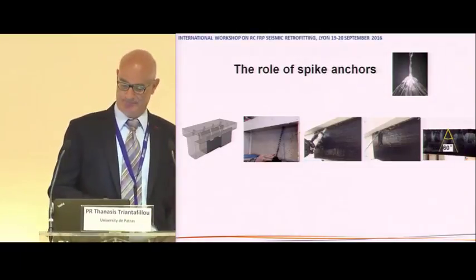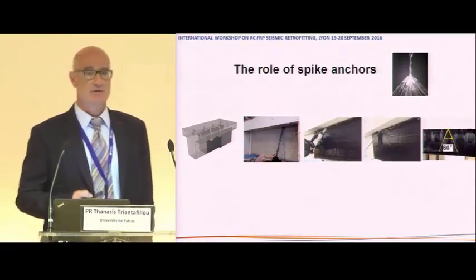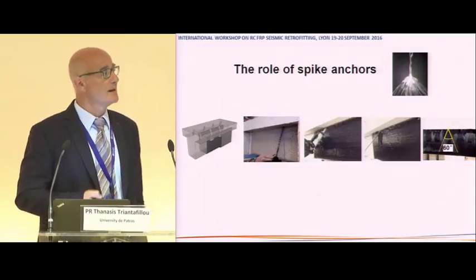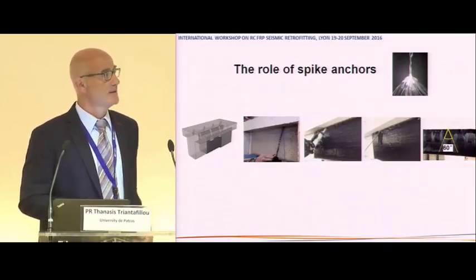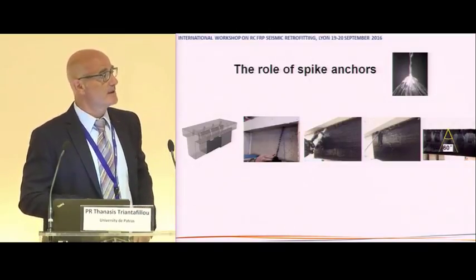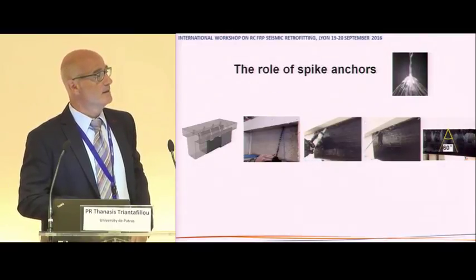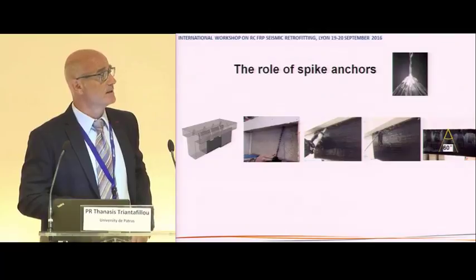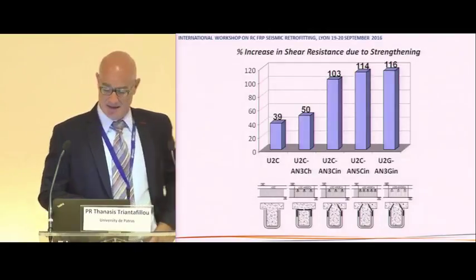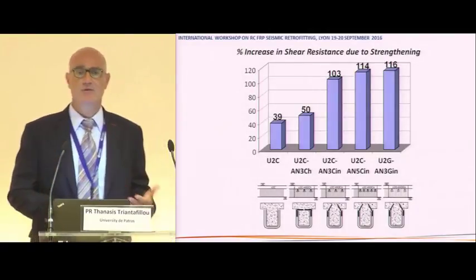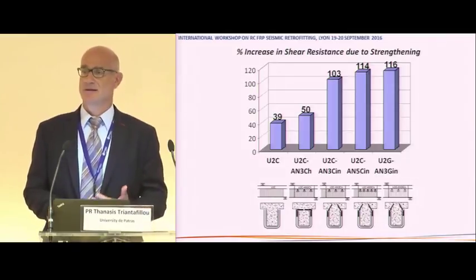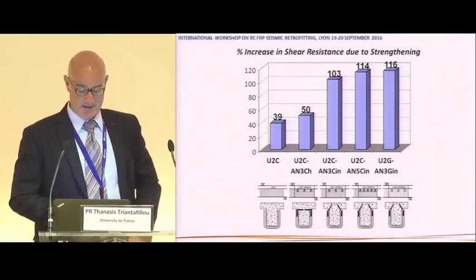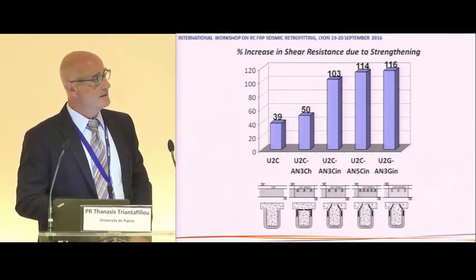One way to exhaust the capacity of the fibers is to combine the system, those open jackets, with anchors, with spike anchors, that is to anchor the fiber, to transfer stresses from the jacket through the slabs in the case of T-beams. Here is one way to prove that these anchors are extremely effective.